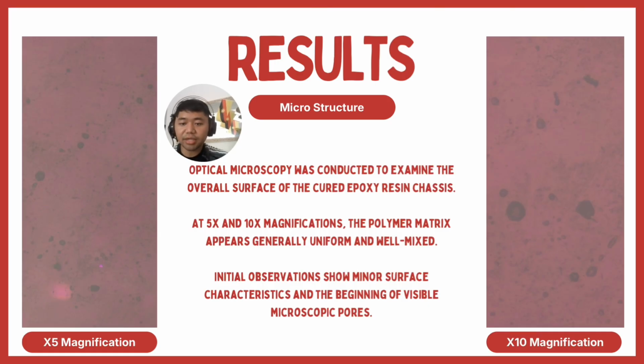In addition to mechanical testing, we also conducted surface morphology analysis on our material using a microscope. We used 5 times and 10 times magnification, which reveal that the polymer matrix generally appears uniform and well mixed, showing that the casting process we conducted was successful and as intended. We also used 20 times magnification so we could see the internal matrix structure in more detail. From what we can detect, there are several defects such as trapped air bubbles or pores scattered within the sample.